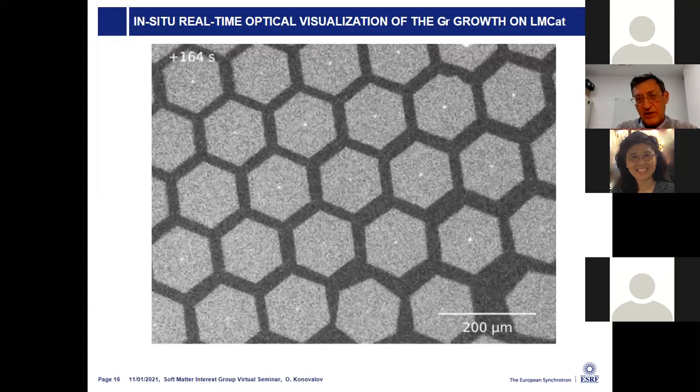What we think is that this is due to a repulsive interaction on a short length scale, because they interact at far distance to align themselves through the capillary interaction, which is a long-range interaction. But then when they go closer, as these flakes are charged, they start to repel. And our interest is to find a process to be able to stitch these aligned crystals together atomically